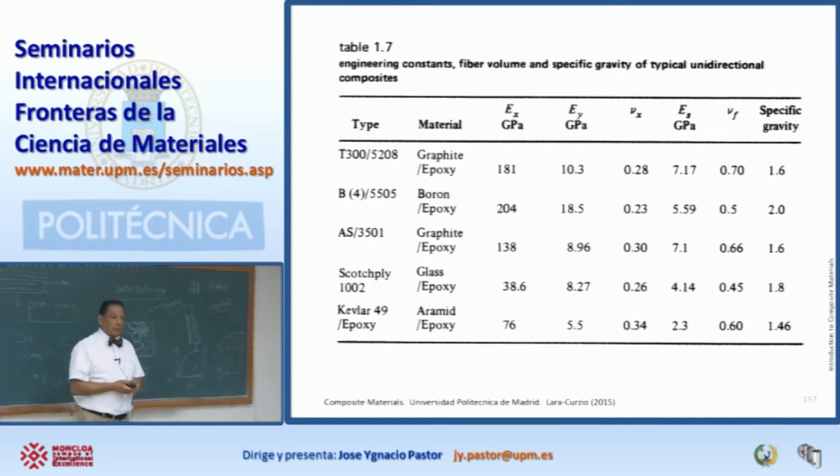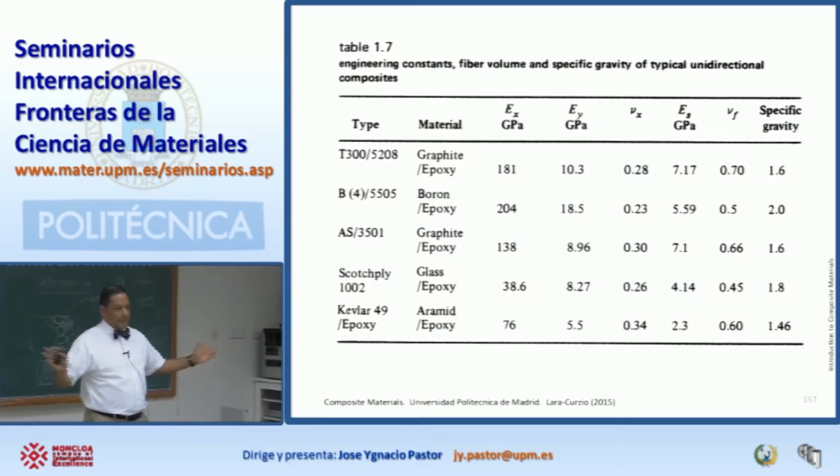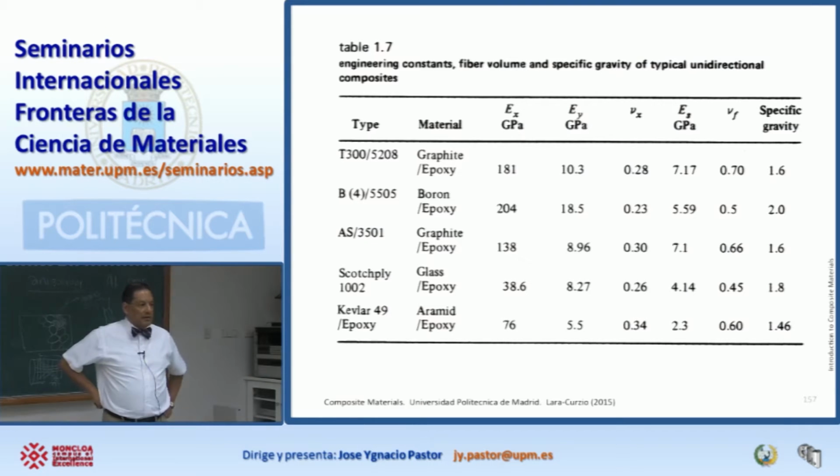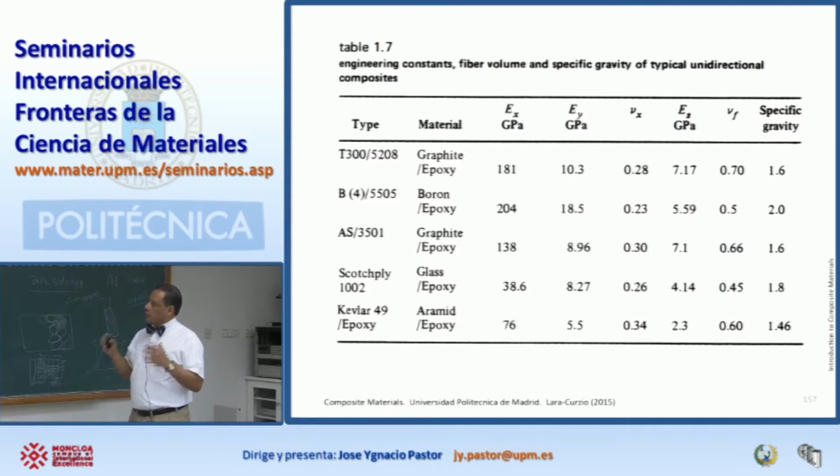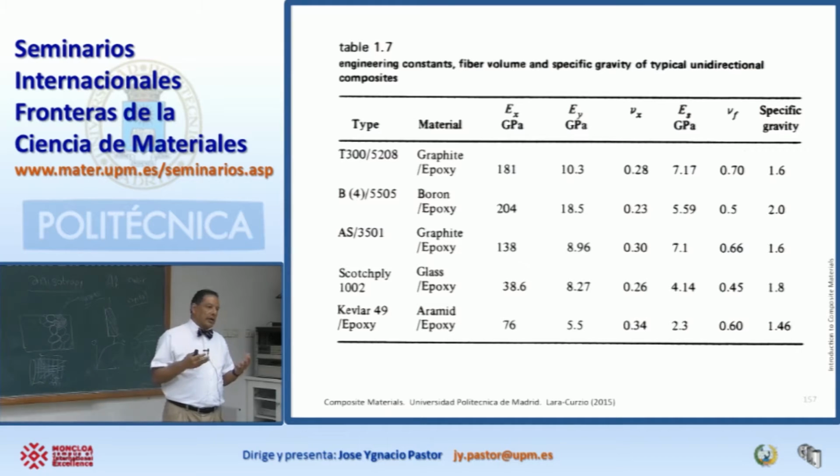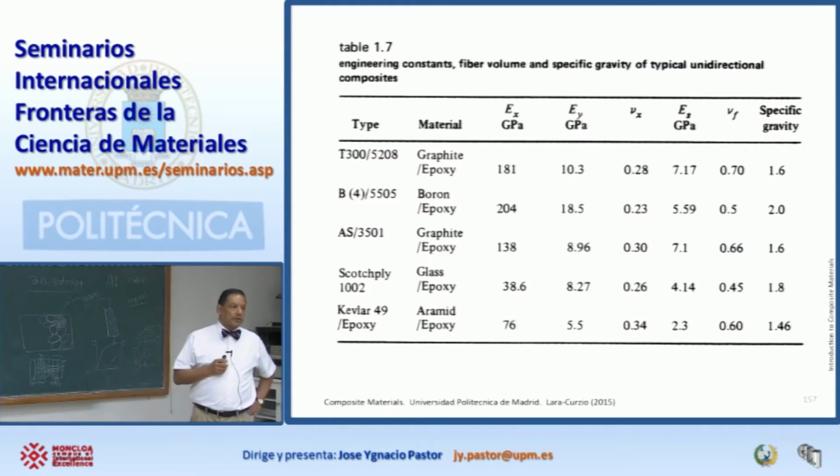Once you have a crack in the matrix, then everything breaks down. It's really a very complicated process. You have fracture mechanics involved. You have frictional interfaces. I mean, it gets really complicated. So these rules of mixtures apply just during the elastic regime. Okay? Any questions?